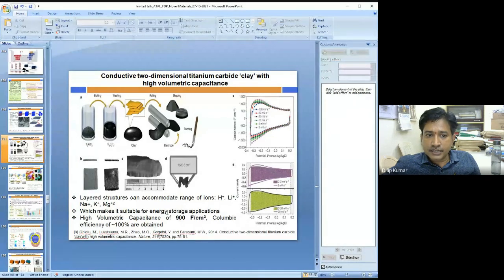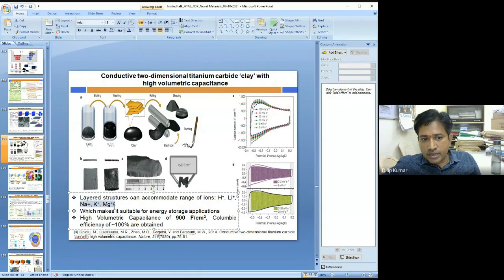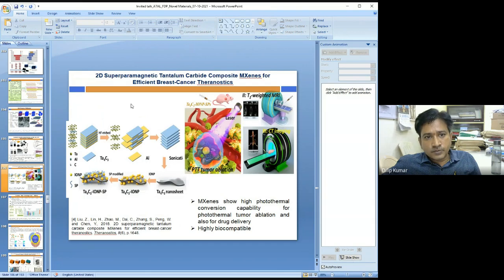And in fact, I can accommodate in these materials the percolation of H+, lithium, sodium or magnesium ions. This is what this article published in Nature shows. And sometimes not only battery or supercapacitor applications, we can look at some tantalum carbide composites, because tantalum again comes under the M category, and X is the carbide or nitride.